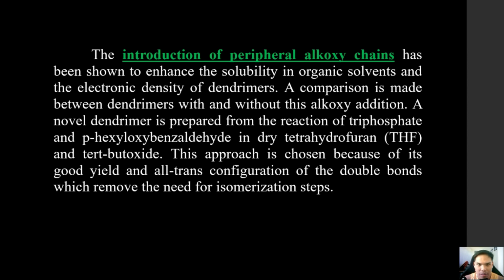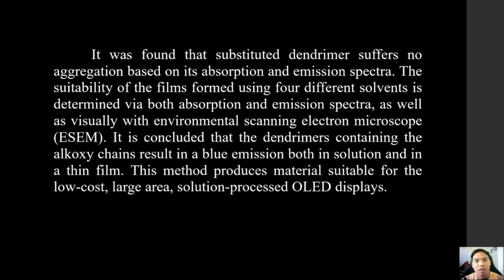A novel dendrimer is prepared from the reaction of triphosphate and p-hexyloxybenzaldehyde in dry tetrahydrofuran and tert-butoxide. This approach is chosen because of its good yield and all-trans configuration of the double bonds, which remove the need for isomerization steps. It was found that the substituted dendrimer suffers no aggregation based on its absorption and emission spectra.